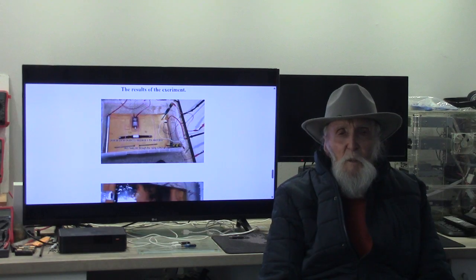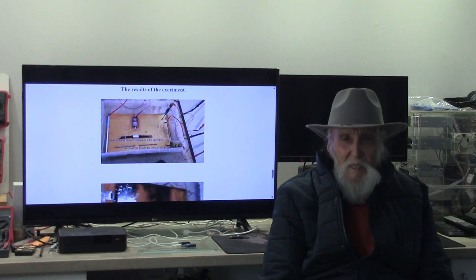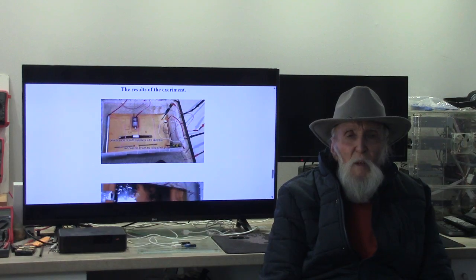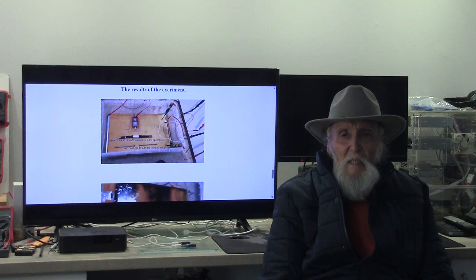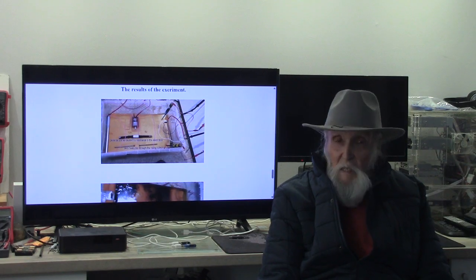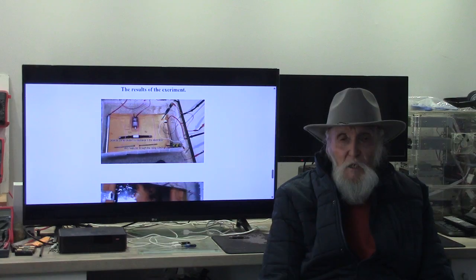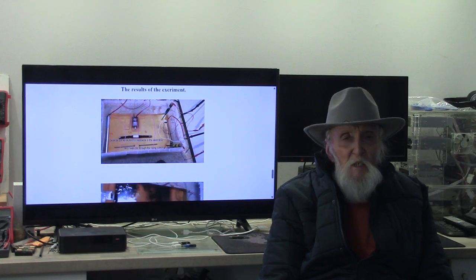As the test continued, the internal pressure eventually exceeded the structural strength of the remaining wall thickness. The vessel ruptured violently, releasing gas in a burst that visually and acoustically resembled an explosion. Importantly, no external detonation or mechanical impact occurred. The rupture was purely the result of internal pressure acting on a corroded and structurally compromised section of metal.